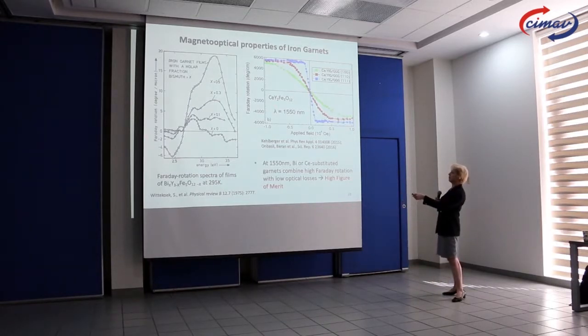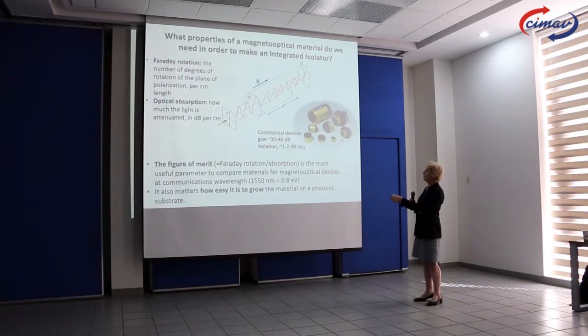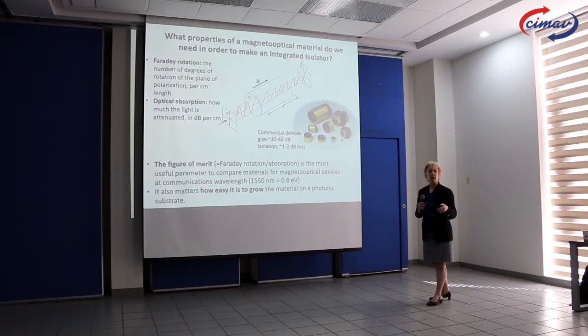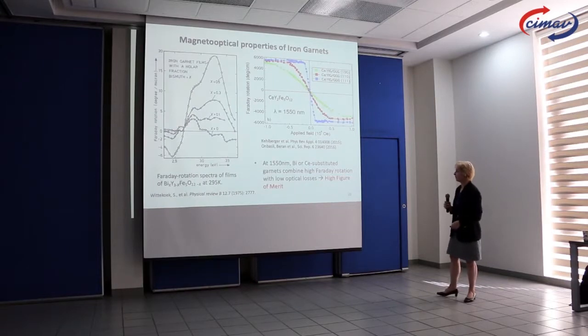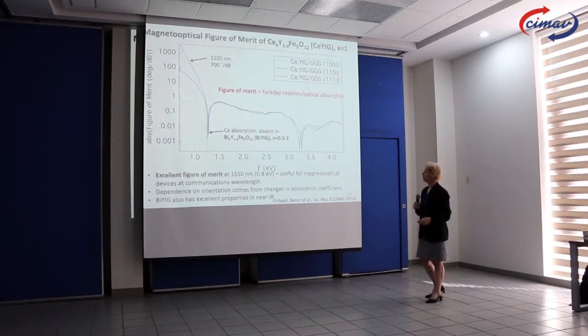Cerium YIG is also a good material, and it has quite a high Faraday rotation. This is thousands of degrees per centimetre. So if you go back to this, you only need 45-degree rotation, so you only need a tiny fraction of a centimetre length in order to get this to work with cerium YIG. So those are the materials we're going to work on, and so we characterised the behaviour of cerium YIG.